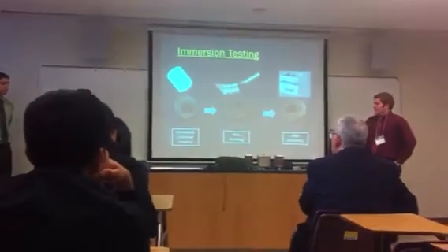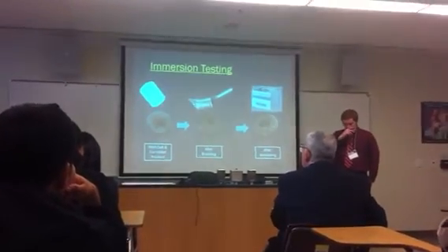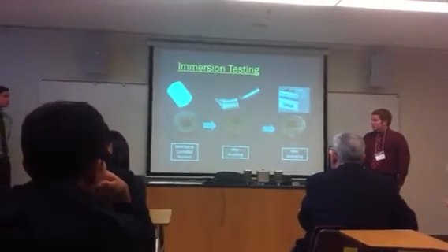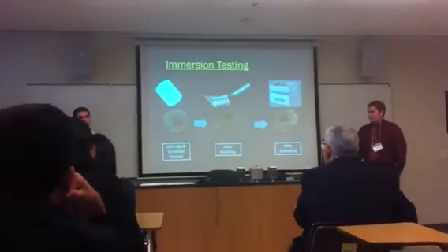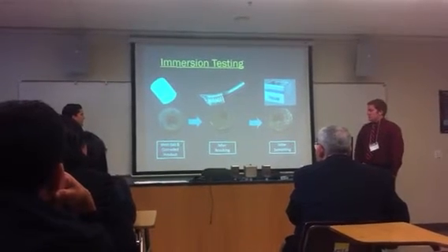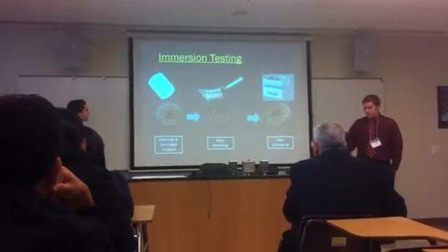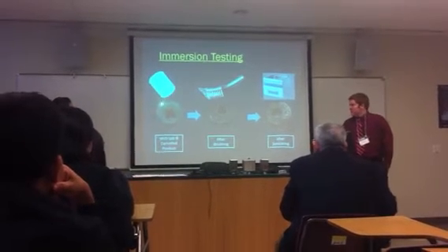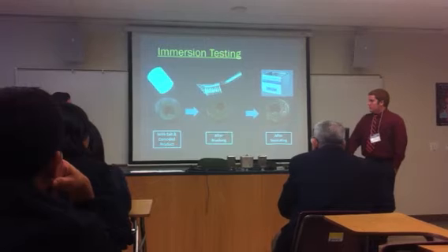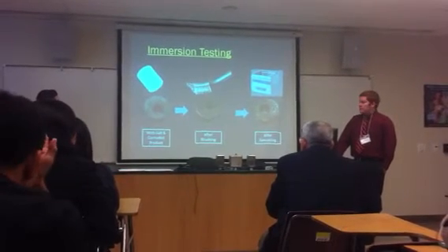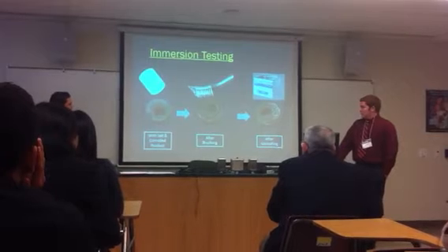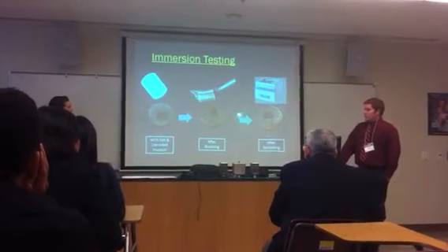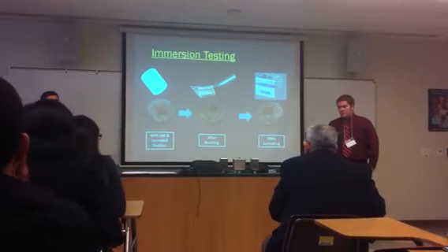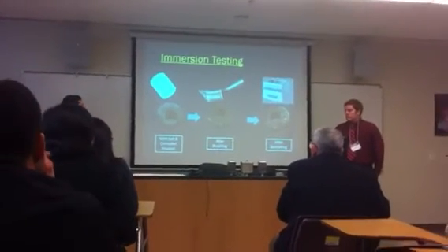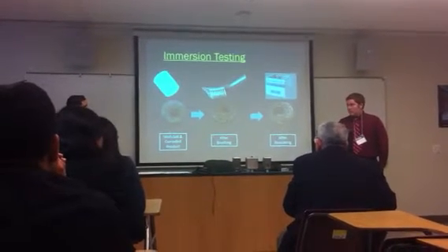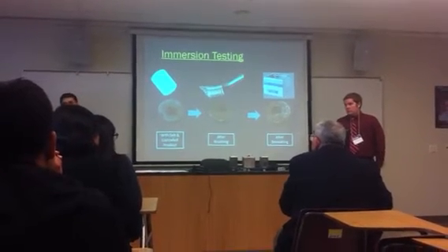Following that, we retrieve the crucible with its components from the furnace, and we extract the sample from the crucible. And following that, we clean the sample so that we can remove the nickel oxide that is on the surface of the nickel 200 by brushing it and sonicating it. As you can see here from the pictures, after we retrieve the sample there is a large amount of nickel oxide on the surface of the nickel 200, and then after we have brushed it, some of the nickel oxide has been removed, and lastly, after we have sonicated, most of the nickel oxide has been removed. This helps us have more accurate measurements of the mass loss per unit area, and so after we have removed most of the nickel oxide, we take several measurements to find the change in mass per unit area.